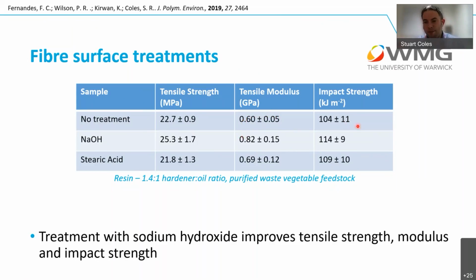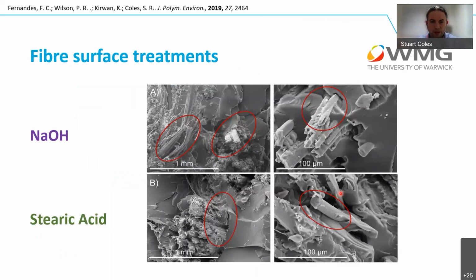But we notice here that the impact strengths of these materials were all actually pretty good. And it was here where we think, well, actually now, this is where our application has to sit, because we found some materials that have pretty good impact strengths that will adapt well to the different fiber types. Just some SEM images here that show potentially the impact of some of the fiber treatments, that they still weren't particularly great. You get fiber pull out with all of them, and that again is largely due to the fact that even those fiber treatments couldn't overcome the incompatibilities at the fiber matrix interface between the fibers and the resins.